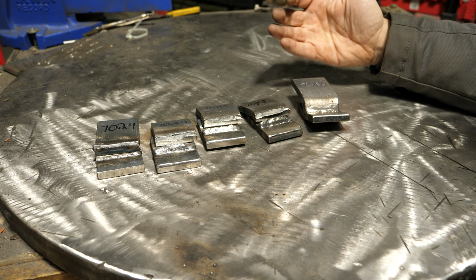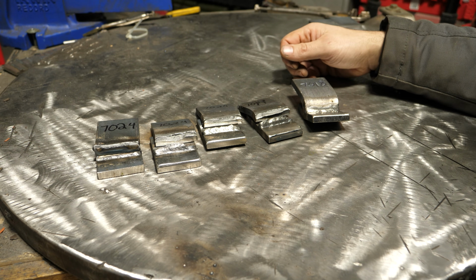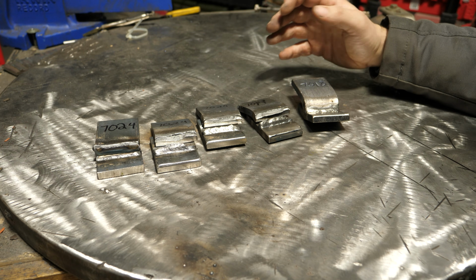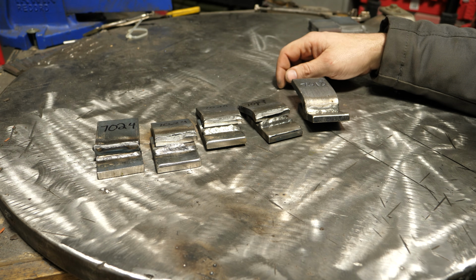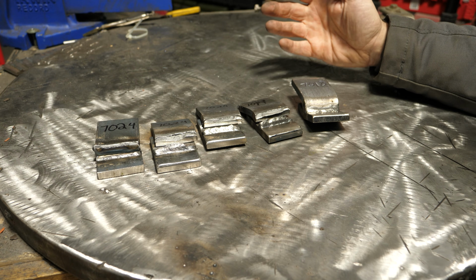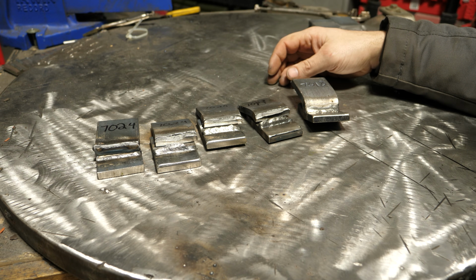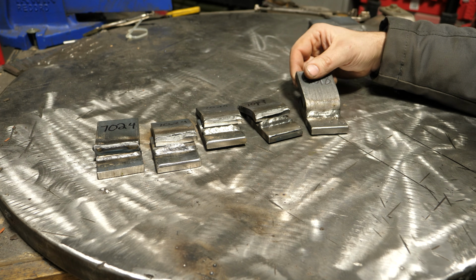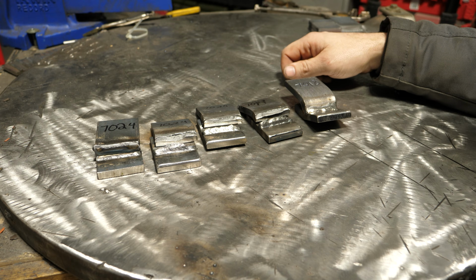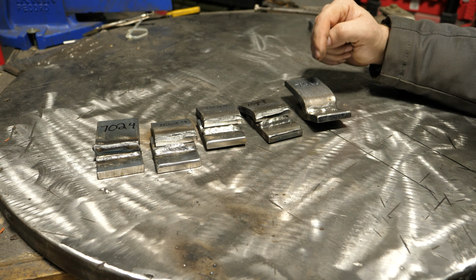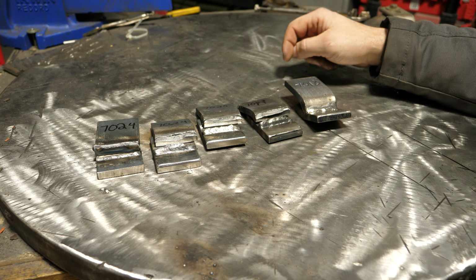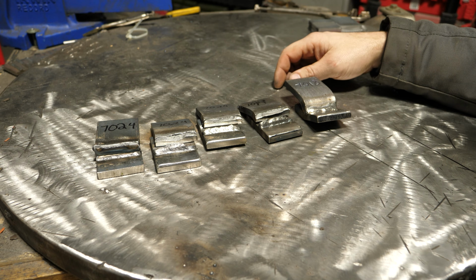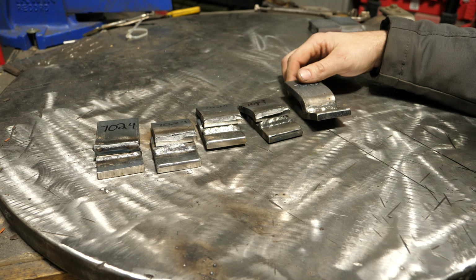But yeah, with that said, I do personally like 70-24. I like the way it runs. I like the bead profile. It looks like chrome when you get a good run with it. So yeah, I like it, but is it great for all situations? Absolutely not. And realistically, is it a substitute for 70-18? I would say on a flat position, filling gouges in something, absolutely, but to actually weld something for strength, definitely not. 70-18 is the way to go, 100% in my opinion, and all the testing that I've done seems to point that way as well.